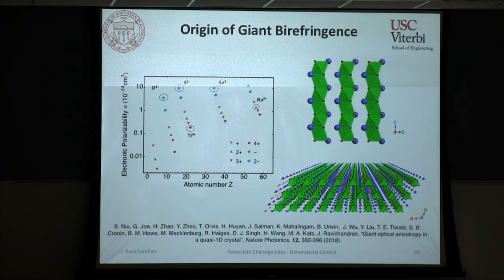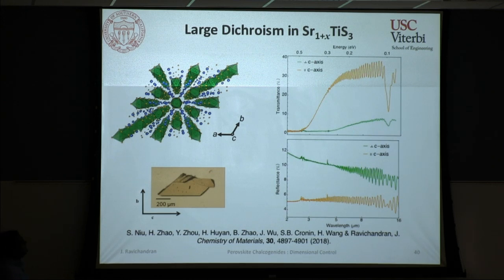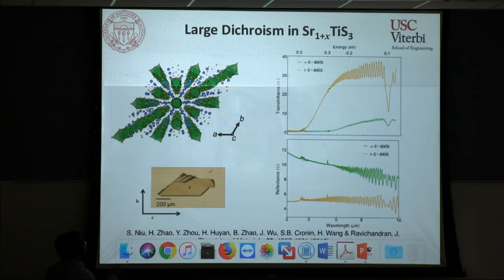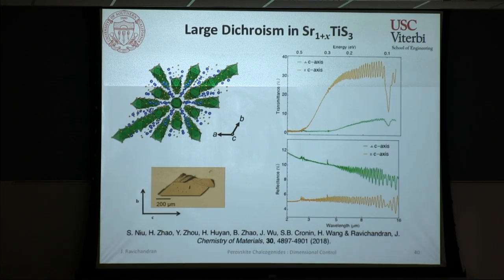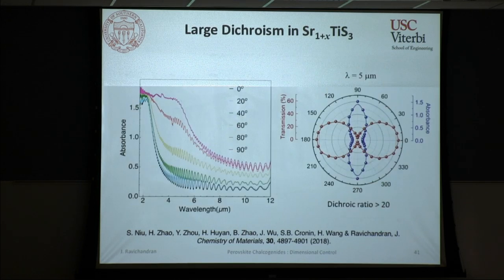So this one is not a one-shot thing. So we were able to grow single crystals of the strontium titanium sulfur 3 compound. It forms a non-stoichiometric, slightly off-stoichiometric material, but nevertheless shows very similar trends in transmission reflection spectroscopy in the IR, and also has high birefringence. We haven't been able to measure the real part of the index because of the size limitation in the absorptive regime, but nevertheless it shows very high dichroism compared to most other materials.